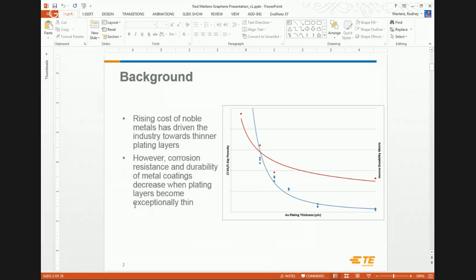Additionally, the thinner that you go with the layers of gold, they're less durable, and that would make sense. You have less gold to wear through. Once again, then you expose the substrate, and you get some corrosion. So as we go thinner and thinner in gold to save cost, we're looking at ways that we can basically help the gold do its job, whether we're adding lubricants on top of it, corrosion inhibitors, doing things underneath the gold, etc. And this is where the graphene comes in. Can we use graphene in some way to use less gold so that it does its job?